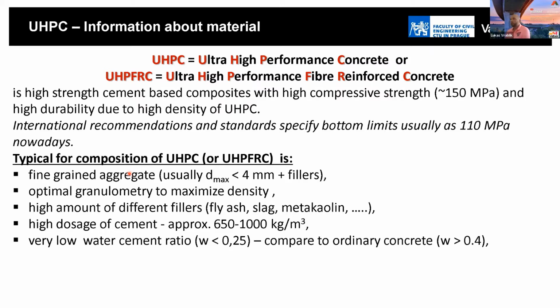It is very good because over time it is possible to obtain something like self-curing of the concrete. If some cracks appear in the concrete, then through the cracks the water can go into the structure, and we have some amount of cement which was not used for hydration. If we add some water from the environment, it is possible to start the process of hydration again. And we have something like, as I said, self-curing of the concrete and closing of the cracks.